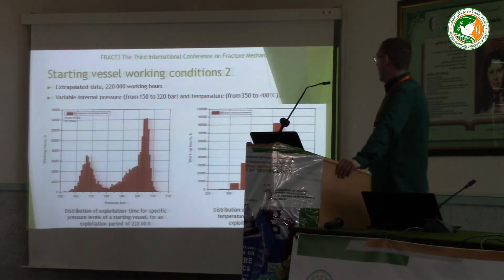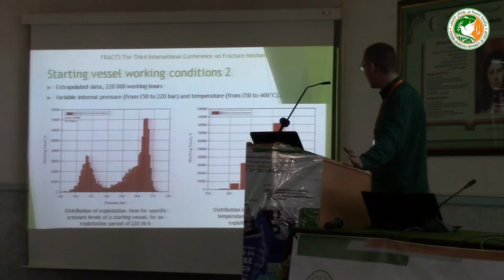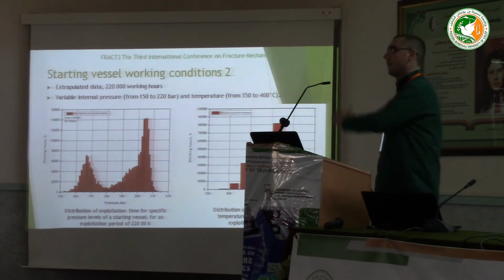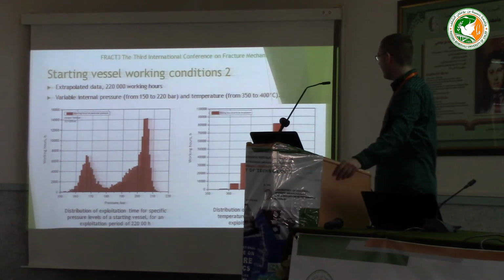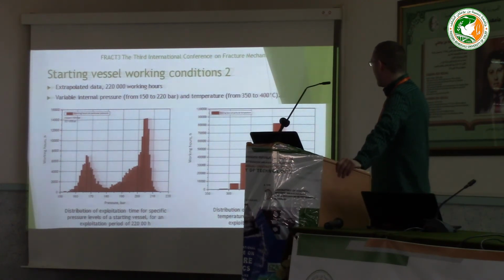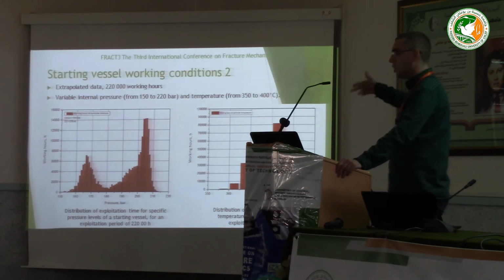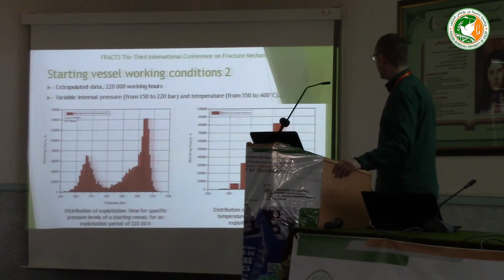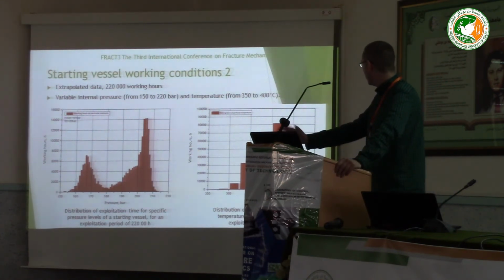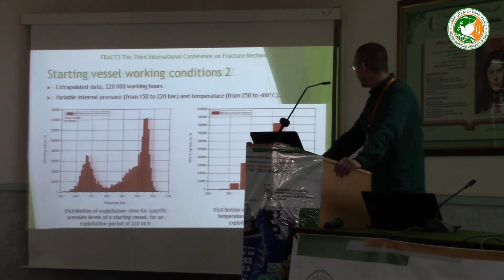Now, we extrapolated this data and obtained data for 220,000 working hours. Okay, we didn't monitor working conditions for 220,000 hours. We extrapolated this data, and you can see the values of the temperatures and pressure during this period of exploitation. You can see that the internal pressure of the vessel was, most of the time, above 200 bars, and the temperatures were in the range between 350 and 400 degrees Celsius.